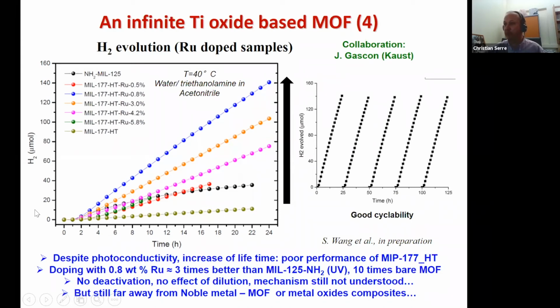So it was a little bit counterintuitive, but we know that photocatalysis depends on multiple parameters. This is not only related to conductivity. But when we increase the ruthenium content, we could see, let's say, a 10 or 15 times increase in the performance when we reach 0.8%. And then, when we increase the ruthenium content too much, it was further decreasing.